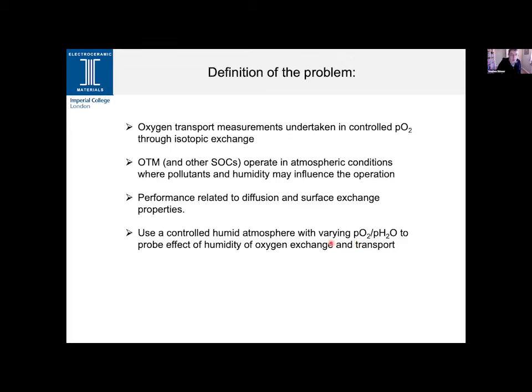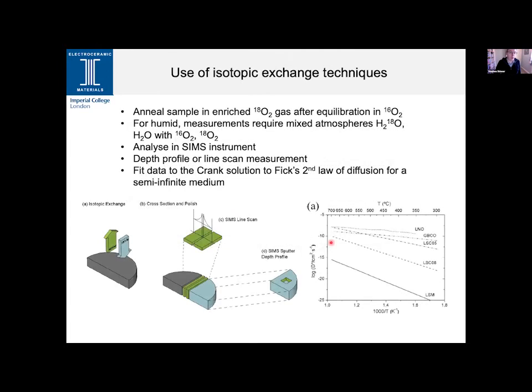Now, for those of you not familiar with the techniques, I'll very briefly go over that. So the idea is that we use an isotopic exchange technique where we anneal our ceramic samples in isotopically enriched gases. So for the dry exchanges, we're using isotopically enriched oxygen, so the oxygen-18 isotope. For the humid measurements, we're requiring the labeled water, so H2 18O. And for the mixed atmospheres, then we're mixing H2 18O with the dry oxygen gases, but also H2O with 18O2. So we have these mixed gas atmospheres.